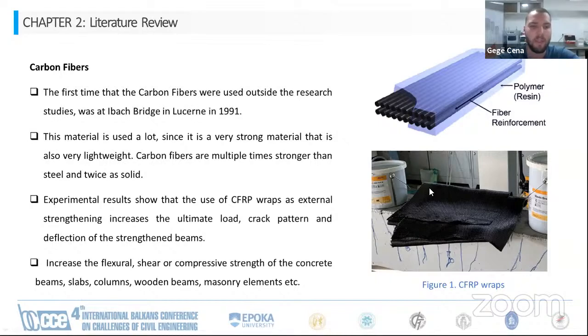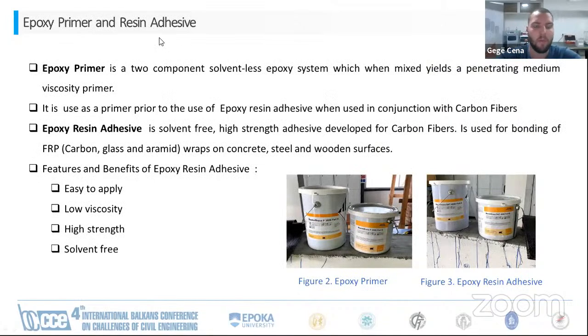The experimental results show that the use of CFRP wraps as external strengthening increases the ultimate load, crack pattern, and deflection of the strengthened beams. Also increases the flexure, shear, and compressive strength of concrete beams, slabs, columns, wooden beams, masonry elements, etc. So this is figure 1. This is the carbon fiber that we used in our experiment. We also used epoxy primer and epoxy resin adhesive.